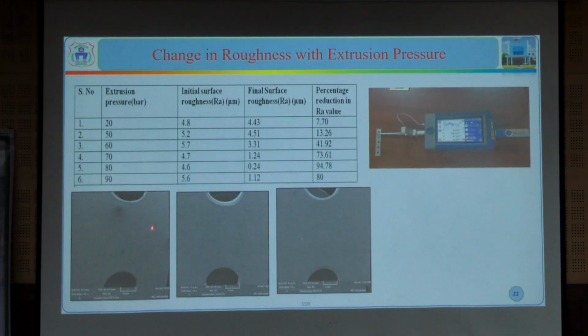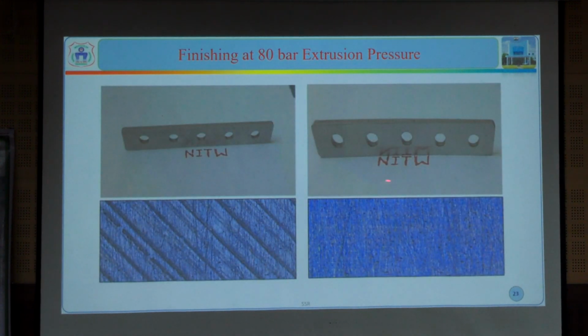And we observed the finishing of the samples by varying the number of cycles as well as the extrusion pressure, and we could achieve some kind of mirror finish before and after abrasive flow machining. Also you can see these are the conventional machining marks. You can see the deep tool marks which are found by conventional machining, and the deep feed marks or deep tool marks are removed by abrasive flow machining. This is not a final achievement. We need to work on improving it. We need a mirror finish, mirror reflection, and also we need to take more complex geometries for finishing.